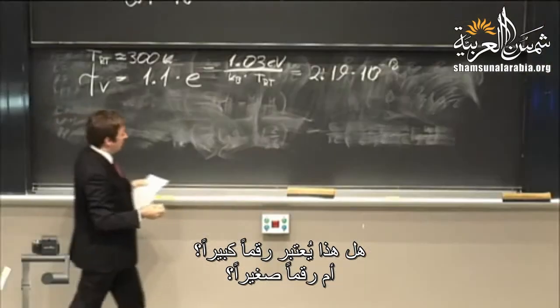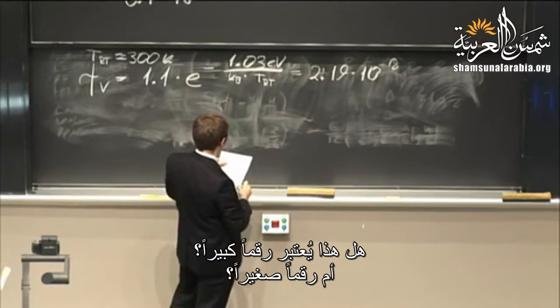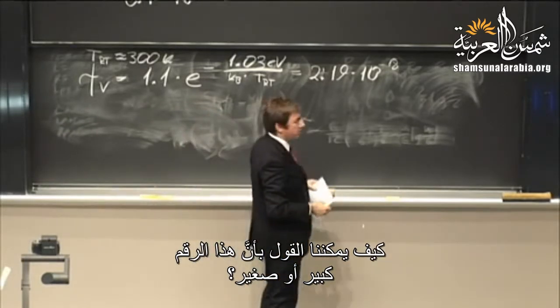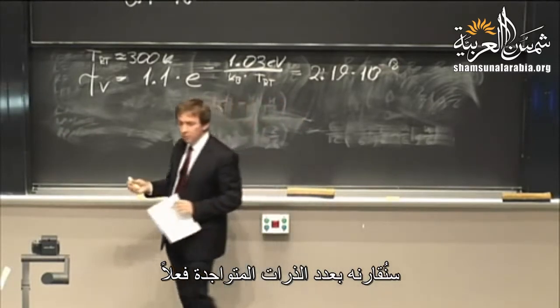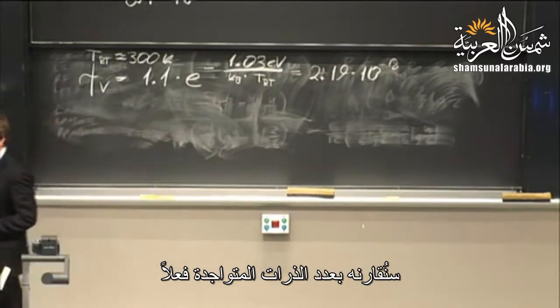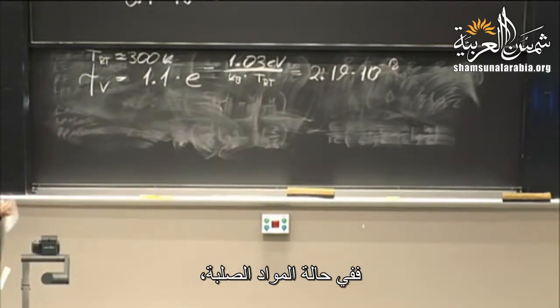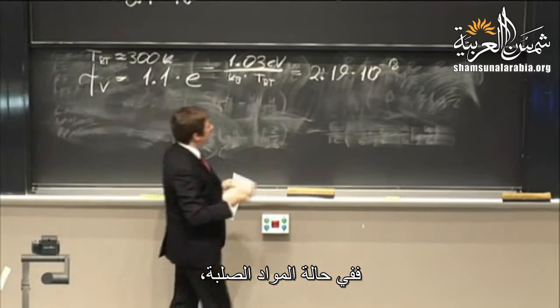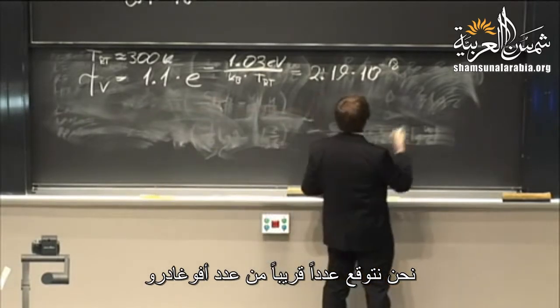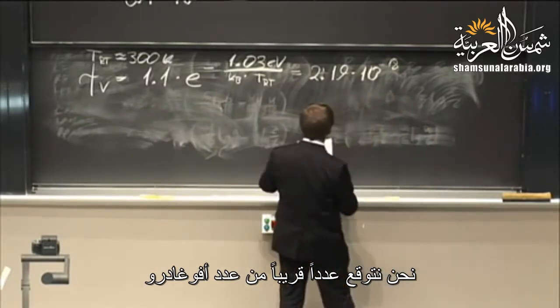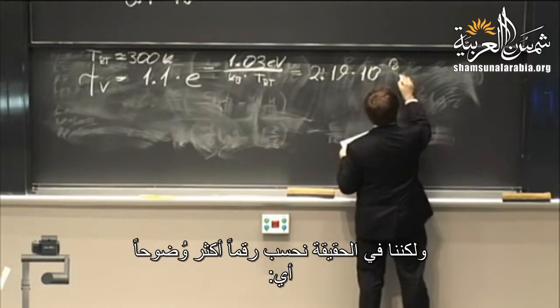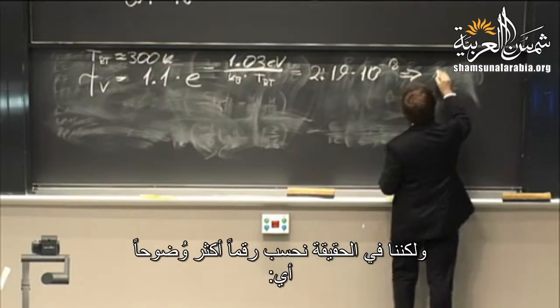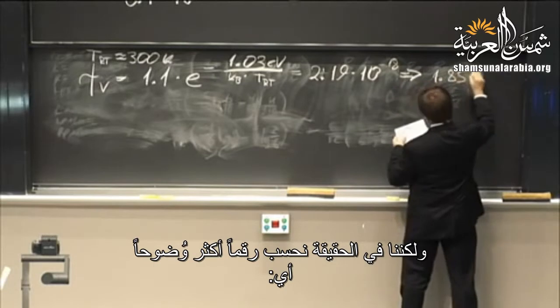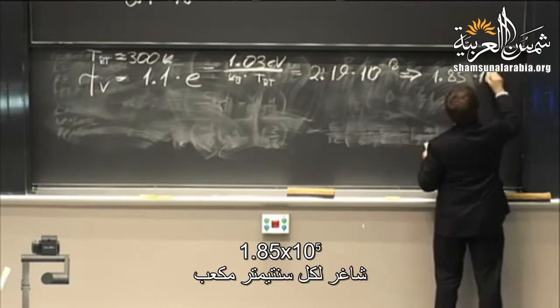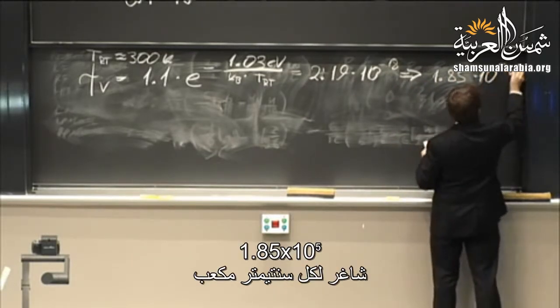Well, is that a lot? Is that a little? How can we determine whether this is a lot or a little? We compare it to the number of atoms that there actually are. In the case of solid materials, we expect it to be compared to something on the order of Avogadro's number, but we can actually calculate more explicitly that this turns out to be something like 10 to the 5th vacancies per centimeter cubed.